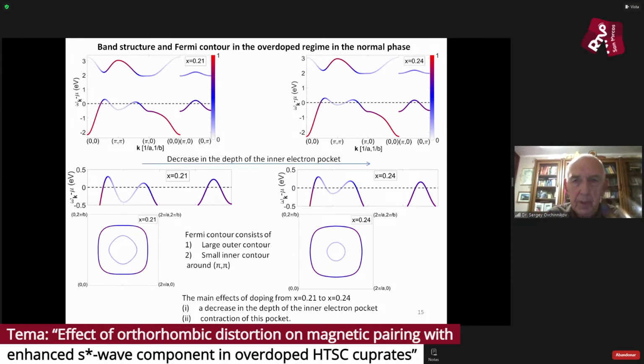Okay, I will close very soon. So here we demonstrate how the Fermi surface changes with doping. 21% is more or less close to the optimal doping, and 24% is more overdoped. There is not a very strong difference, just a quantitative difference. For example, for both dopings, we have a large external surface here and here. But the pseudogap surface is larger for 21% and is smaller for 24%.